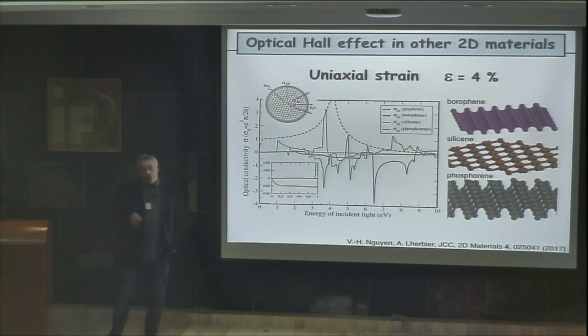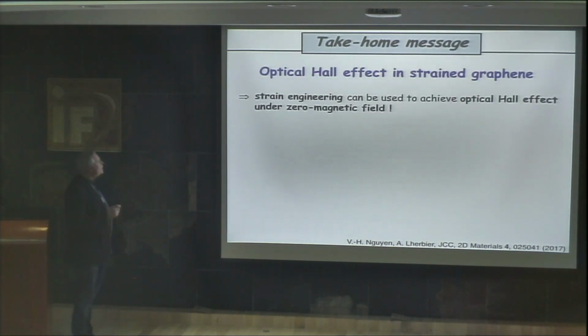We have tried to use this model also for other types of 2D materials like borophene, silicene, and phosphorene, and we see that sigma xy is also very complicated. We are still investigating this type of curve because it's quite chaotic and very complicated to explain. But anyway, when you apply strain on these 2D materials, you also observe this kind of optical Hall conductivity. Okay, with that I finish the 7th point, the optical Hall effect in strained graphene.